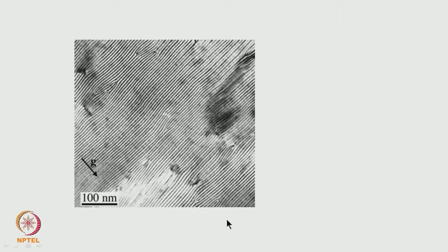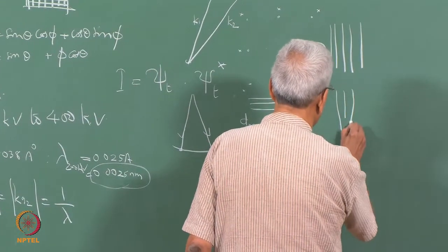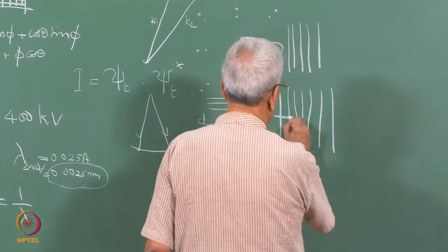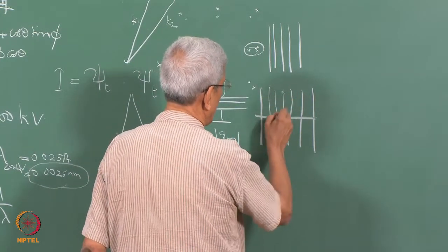There are many applications. One of the first applications was that this Moiré fringe pattern has been used to find out how, in the case of an edge dislocation, when there is an extra plane, this gives rise to an appearance similar to the planes. If you remember, generally when we draw an edge dislocation, this is the slip plane, and this is the extra plane, the upper half above the slip plane.